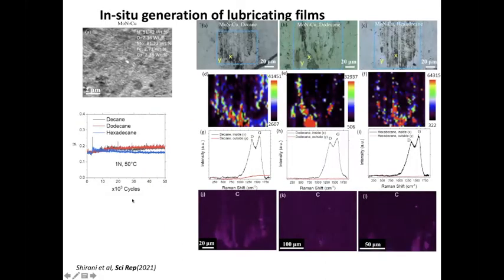So for example, in one of the recent studies, which we just published last year in 2021, we used copper as the catalytic metal to provide this reconstruction of the materials from the decane, dodecane, or hexadecane environment and get the protection of the surfaces. In this case, the coefficient of friction wasn't really dropping to superlubricity, but what we've been able to get is to drop to the zero wear regime, because our wear track is completely replenished and constantly reconstructed by using these hydrocarbons provided from the environment.